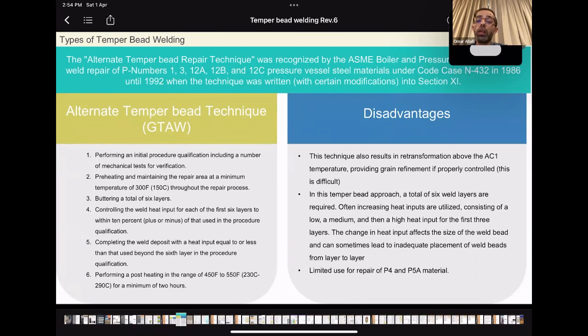by preheating the repair area to 150, buttering a total of 6 layers. So in each layer, you are increasing the heat input for the first three layers. So you use a higher heat input in the second layer than the first one, and again a higher heat input for the third layer compared to the first and second layer. So this will result in increasing the temperature of the base metal above the lower critical temperature.